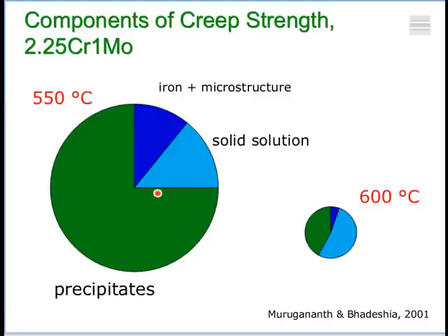Okay, so the point I'm making here is that when we calculate the strength, it is not constant as a function of temperature, and the contributions from the different components will change as we alter temperature. And that is why we hardly ever use ferritic steels at temperatures in excess of 600 degrees centigrade, because the strength collapses as we raise the temperature.